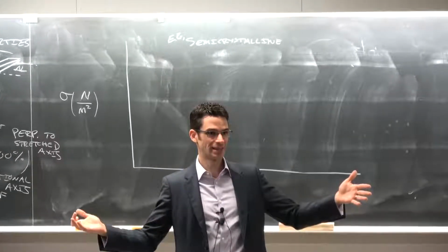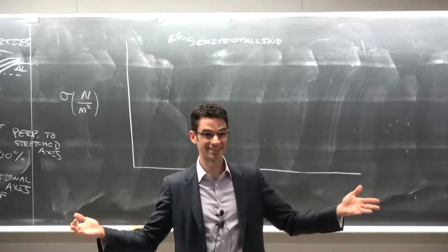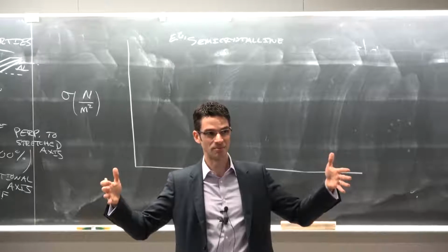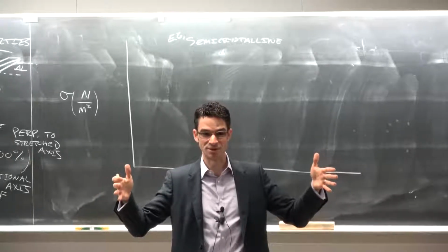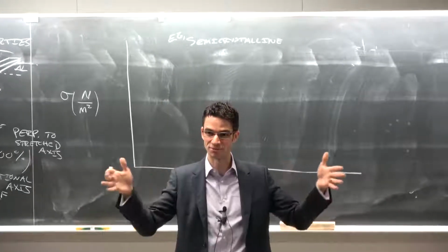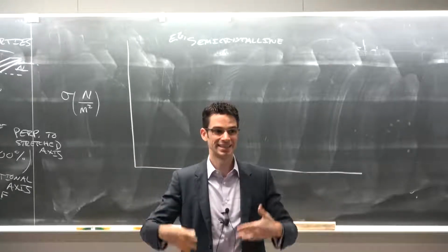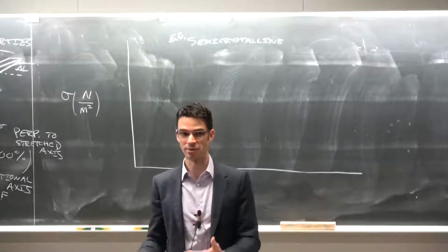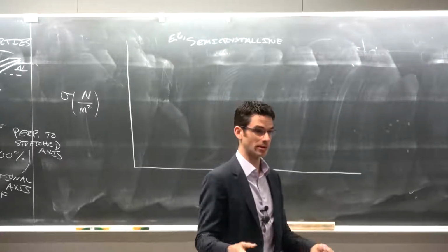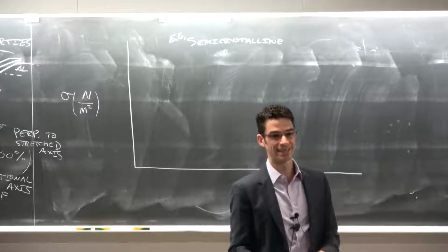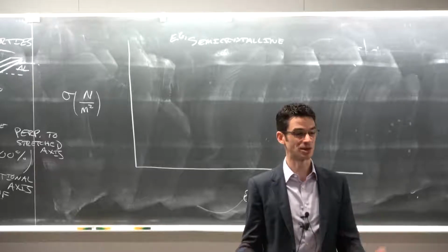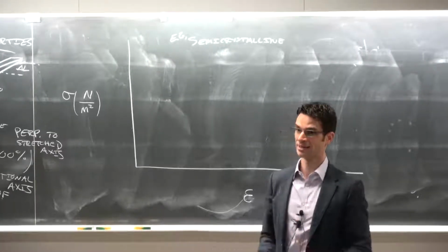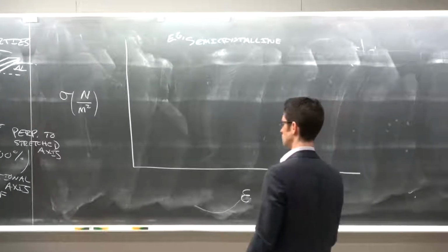But it does. There's always some oscillation, and if it goes further toward the contracted state, the entropy increases. So in the elastic regime of a semicrystalline or an amorphous polymer, they call it an entropic spring, because it's really a statistical argument for why the polymer film wants to contract.